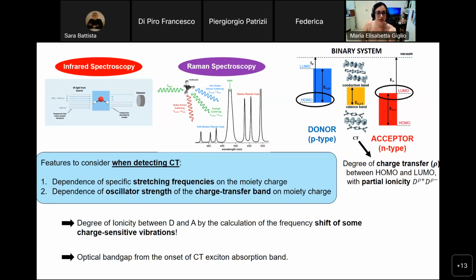So basically, we can calculate the degree of ionicity, so the degree of charge transfer between the donor and the acceptor, by calculating the frequency shift of some charge-sensitive vibration in infrared spectroscopy as well as in Raman. And then we can also calculate the optical band gap from the onset of the charge transfer exciton absorption band.